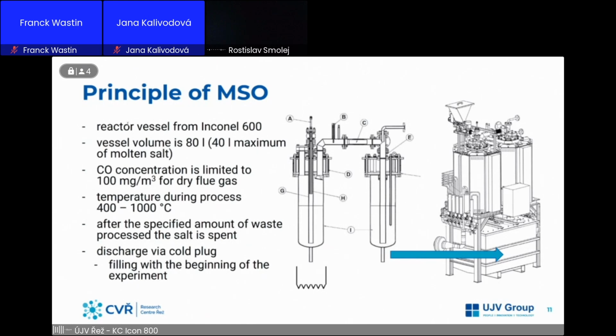But in the end, with each experiment and whichever waste we are putting inside the reactors, the salt is becoming spent due to the ashes or due to the acidic contaminants within the waste. And as the salt is spent, you need to properly dispose of it. You can dispose of it by the small tubing at the end of the reactor, which is called the cold plug. The cold plug is filled before the experiment. It's cooled from the bottom. And after the experiment, when the salt is spent, this is coming from the fully analyzed waste, it goes to the water tank, which is under the two reactors. The water tank is filled with water, and partially the salt is dissolved after the pouring, and then you can process it in a different technology, in the ETL, or properly dispose of it via the stabilization process.